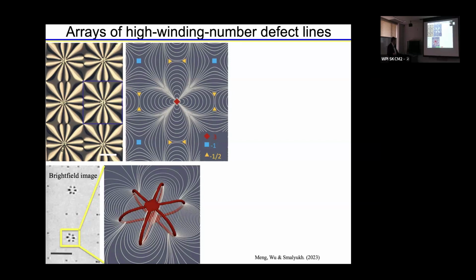What that corresponds to is, remember, the +1 vortex was split into 2 half integer ones to reduce free energy. The +3 is split into 6 half integer ones because that allows it to reduce free energy dramatically, because 6 to the power 2 is 36, whereas if you split them this way, you reduce it 18 times, right? So then what it means is that in the field configuration, on the large scale, we have everything as we pattern it, but locally, there is an additional feature that corresponds to splitting of the core of the +3 vortex into 6 half integer ones. And we will see that this effectively creates revolving gates that will control optical solitons in a very interesting way.